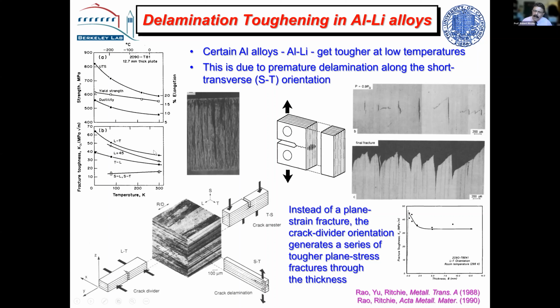And the question was, why do they do that? And this is a kind of an interesting phenomenon you don't see a lot about. When you look at the fracture surface, you see these sort of delaminations on the fracture surface. And it turns out these alloys have a sort of pancake structure. It's a very, very layered structure. And if we look, this is called the short transverse orientation.